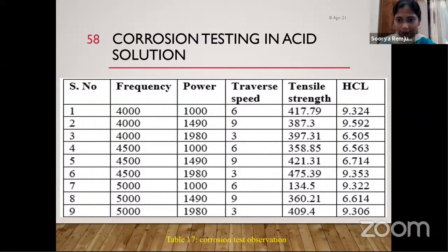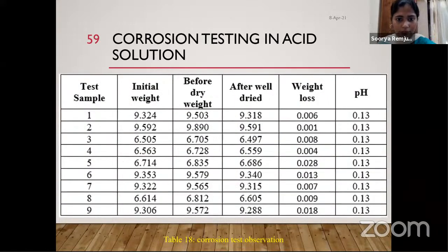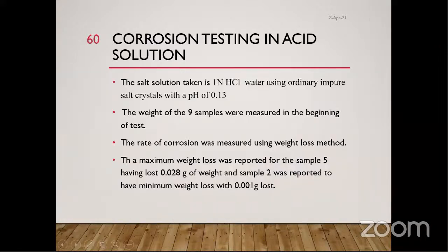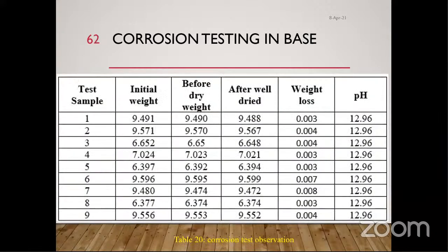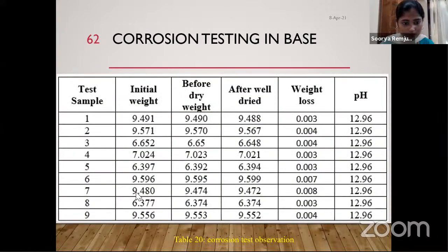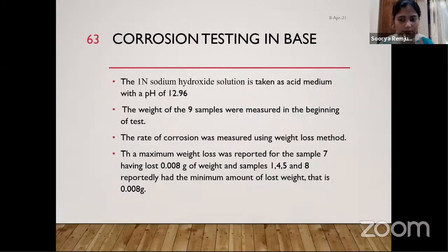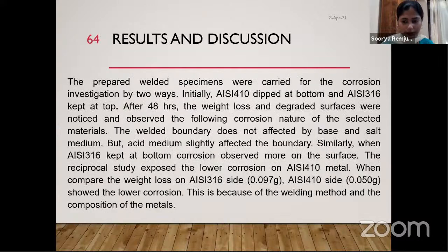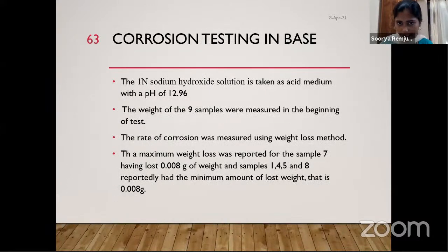So for acid, this is what we observed. Comparing before weight and after weight, the maximum weight lost was for sample number 5, and the minimum was for sample number 2. Then similarly in base, the maximum weight was lost by sample number 7, and the minimum by 1, 4, 5. Multiple samples had minimum weight loss reported. So this is my entire experiment.